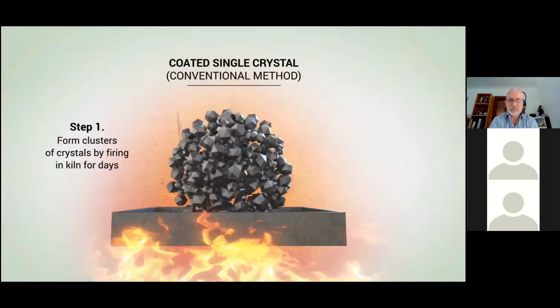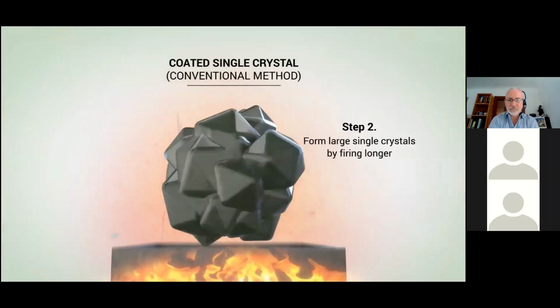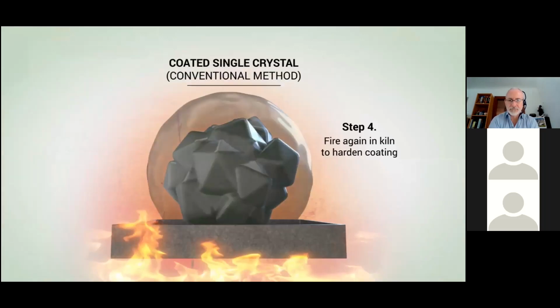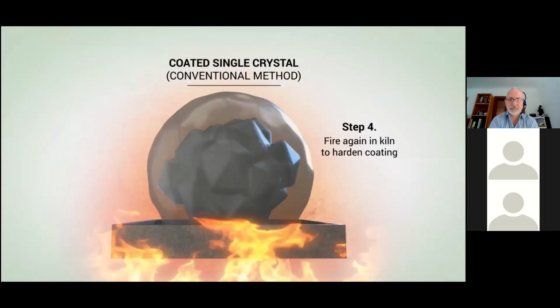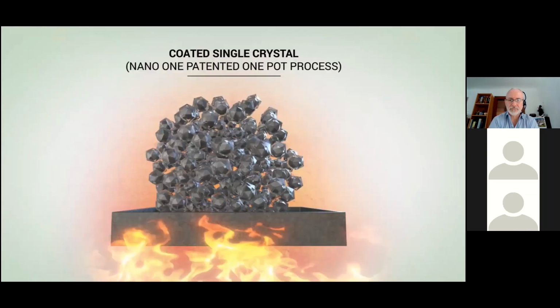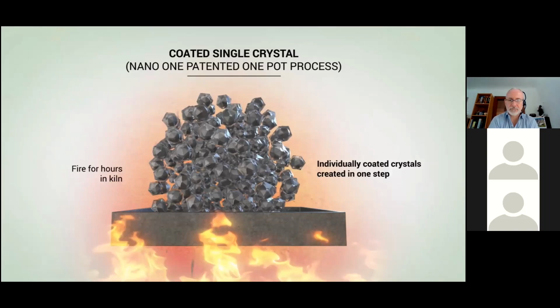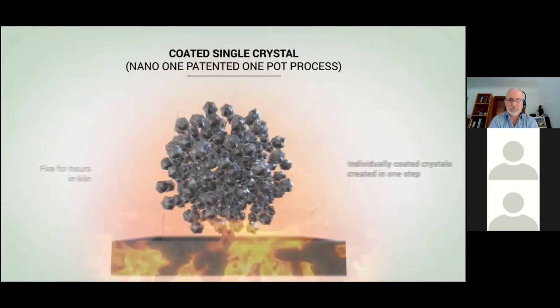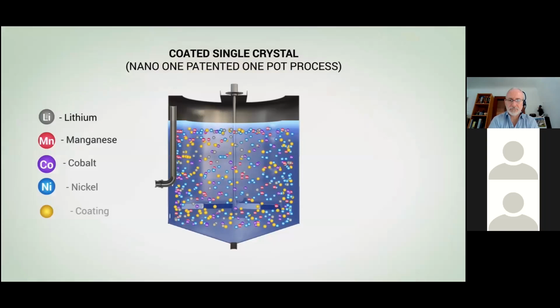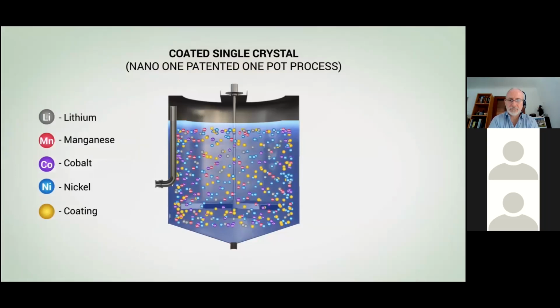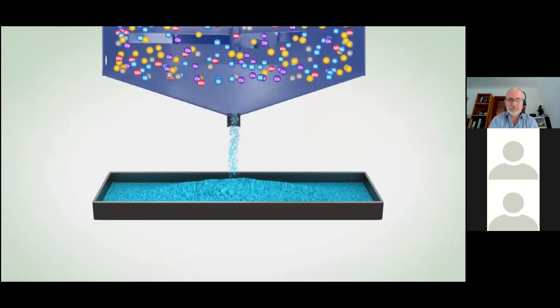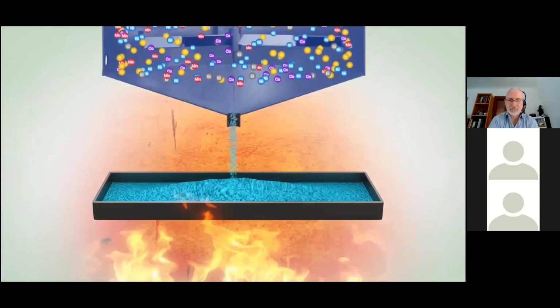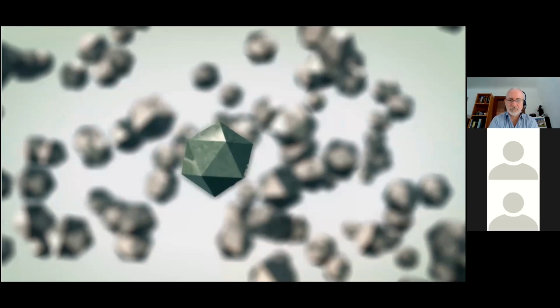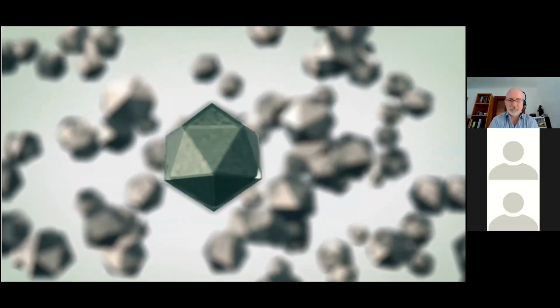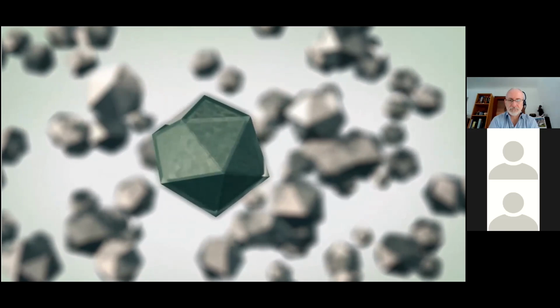Single crystal cathodes are less prone to cracking and can be formed with extra heating prior to coating. But this adds even more cost and complexity. Nano One's innovation solves all of these problems by forming single nano-sized crystals and a coating simultaneously. It begins with Nano One's patented one-pot process, where lithium is mixed in a single reaction with coatings and other metal feedstocks to produce a composite precursor powder. When heated, it transforms into coated single nanocrystals with no extra steps, no excess heat, and no added costs.